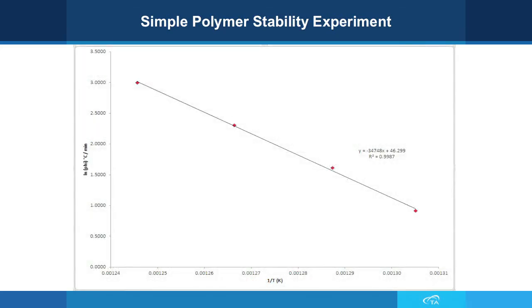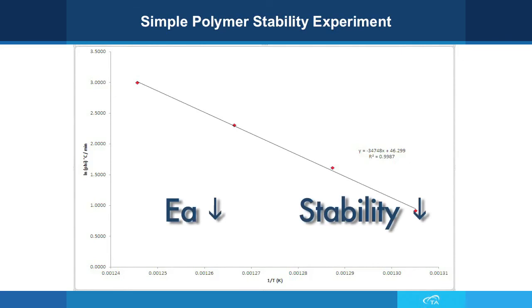You can see that our function is very linear. Our correlation is very high — 0.9987 for our R squared. So our data looks very good, and obviously the lower the activation energy, the more susceptible this material would be to degradation, or potentially the less stable this material is. This obviously is a very simplistic method for doing this. If you need more detailed kinetics information, may I suggest the specialty library by TA Instruments — contact your local sales representative for a demo.